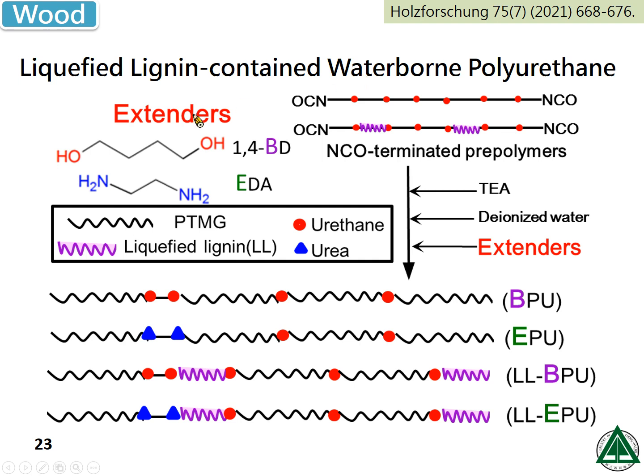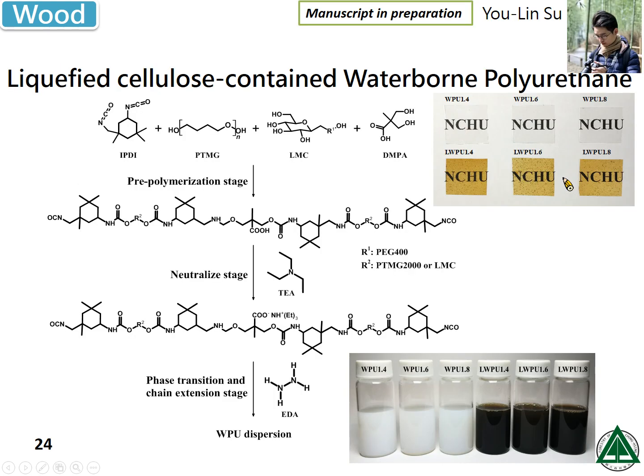Moreover, we compare two kinds of chain extender. The first one is 1,4-butanediol, and the other one is ethylenediamine (EDA). So two kinds of extender and two kinds of polyol. One is PTMG, and the second is liquefied lignin. We think we can synthesize a new type of waterborne polyurethane containing some lignin. The result shows the lignin and extender can change the property. Moreover, we also use liquefied cellulose to synthesize waterborne polyurethane. The result shows liquefied cellulose has a structure different from PTMG, so it can control the property of waterborne polyurethane. Especially, we can increase the hard segment ratio.